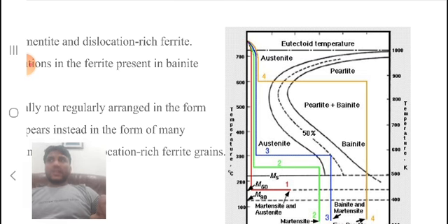These plots show the greatly increased toughness and ductility of carbide-free bainitic steels, and the sharp drop in toughness in bainitic grades containing intra-lath carbide. Sometimes the bainitic grade steel structures are divided into four types, B1 to B4.